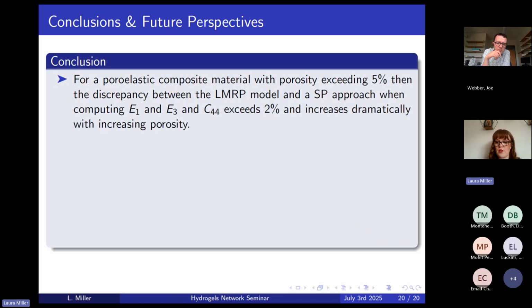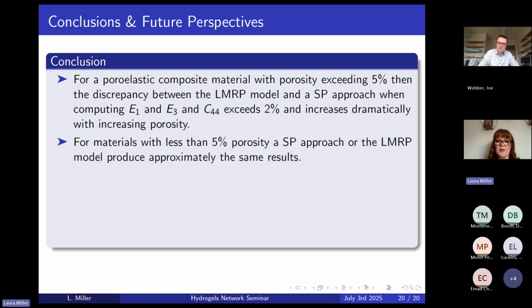Just to provide you with a few conclusions to this work: for a poroelastic composite, that was my new work, my new model, with porosities exceeding 5%, the discrepancy between my new model and a standard poroelastic approach when computing the different Young's moduli and the shear exceeds 2%, so we should use my model rather than the standard poroelastic approach. For materials with less than 5% porosity, either model setup can produce approximately the same results.